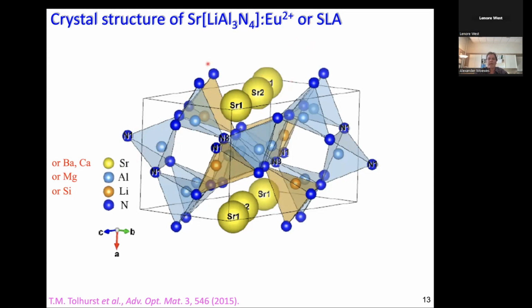And now the bottom line is the structure here remains the same, except for small modifications of the distances. And you can now switch, say, strontium with barium or calcium, aluminum with magnesium, lithium with silicon, and the nitrogen always remains the same. So we don't go into the details. I have structural pictures about exactly those, but the point is you have a similar class of materials, you only change elements, and that allows one to tailor or cater to different luminescence properties.